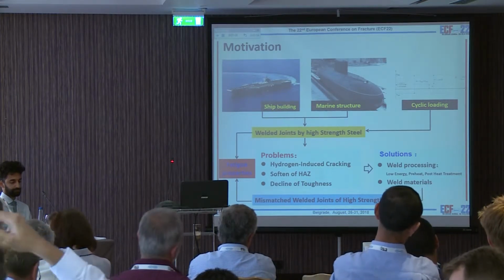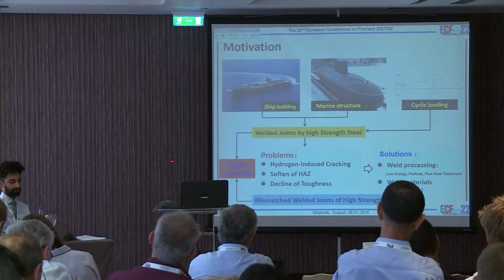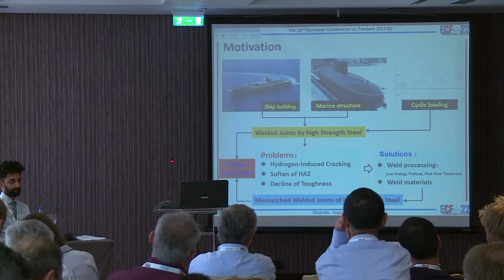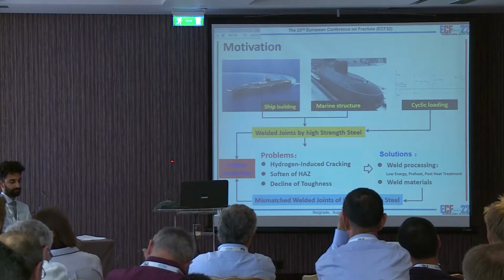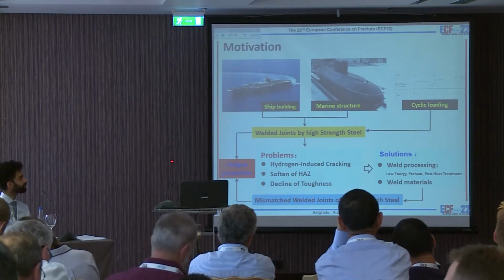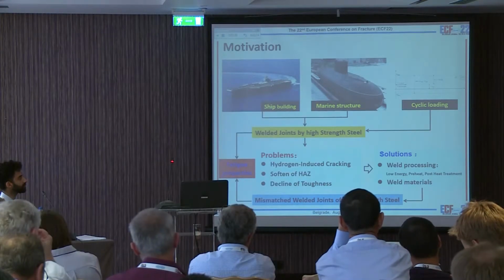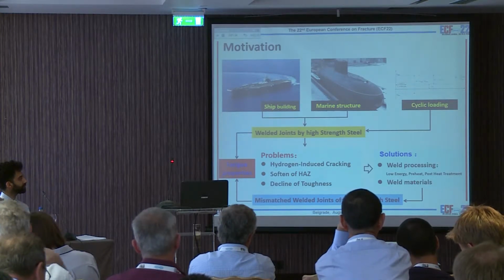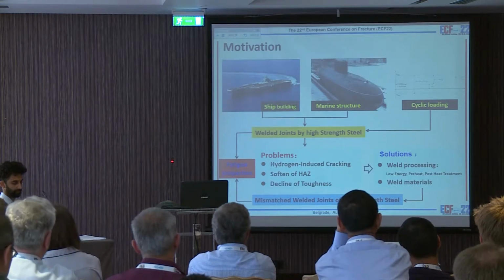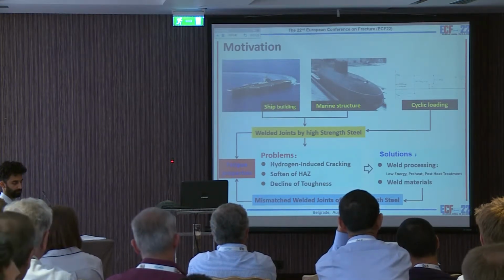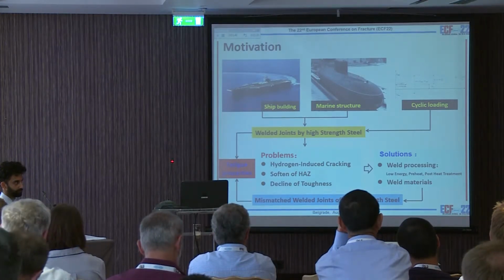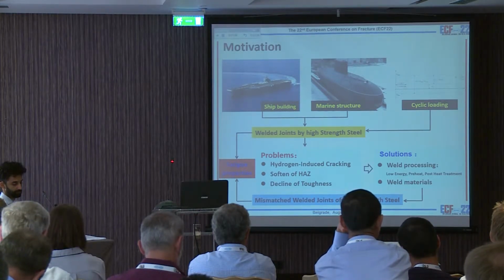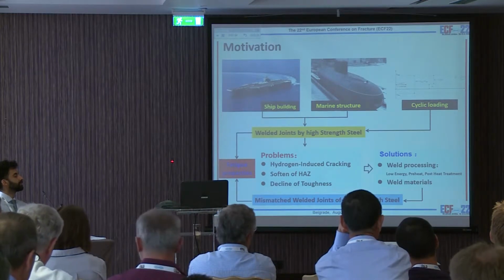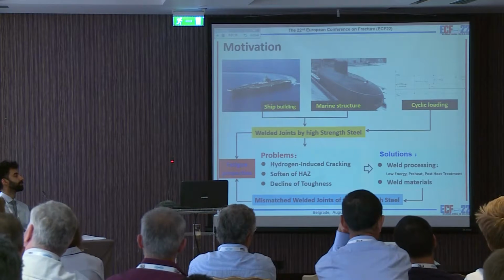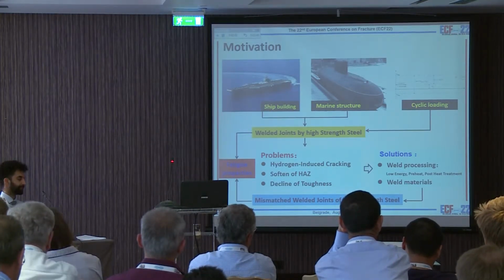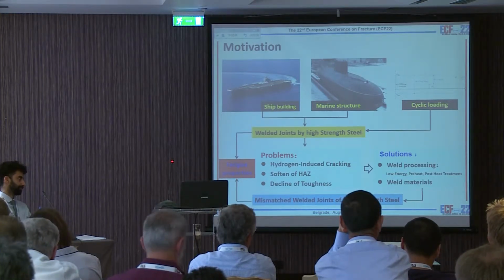So in order to give a solution for these disadvantages, we can change the welding process to improve the welded quality, such as lowering the energy of the welding process, doing preheating or post-heating treatment, or HFMI. Another way is to change the material, decreasing the weld strength and increasing the ductility. So for this welded joint, a mismatched welded joint can occur for the high strength steel. My project is to study the fatigue property of the mismatched welded joint.